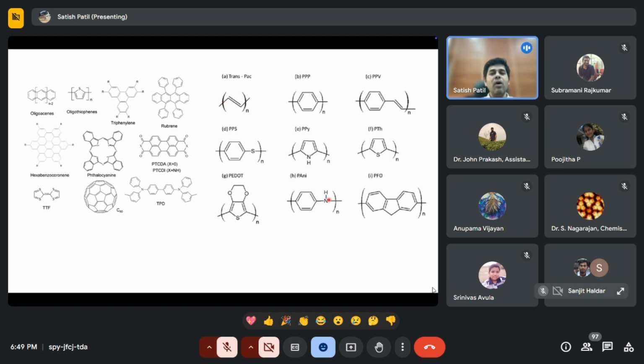However, in the case of polymers, you can dissolve these materials in a common organic solvent and make a very viscous solution. And that viscous solution you can coat on any surface. So that is the major difference. You can grow single crystals of these small molecules. Growing single crystals of polymers is also possible, but it is very challenging, because these materials have a large polydispersity index. Every repeating unit is not very similar. As a result, it is difficult to grow single crystals of polymers.